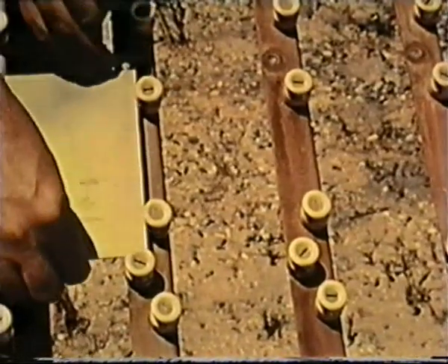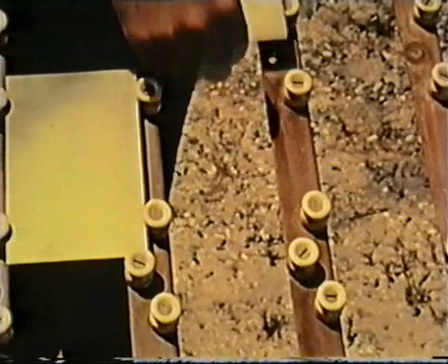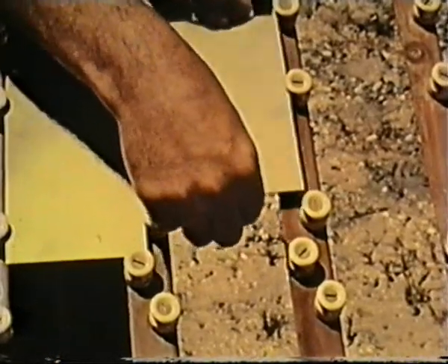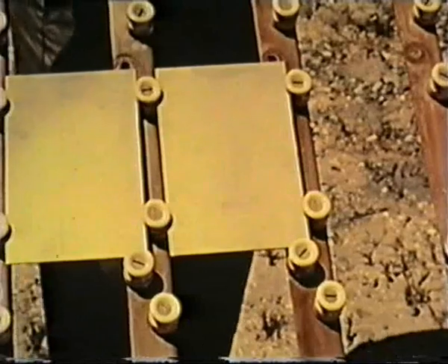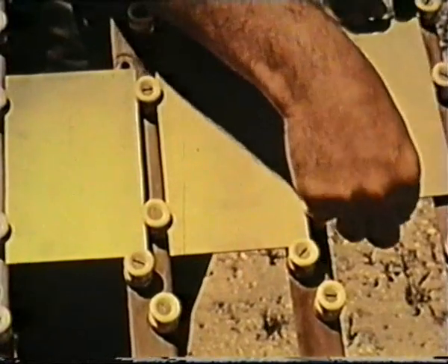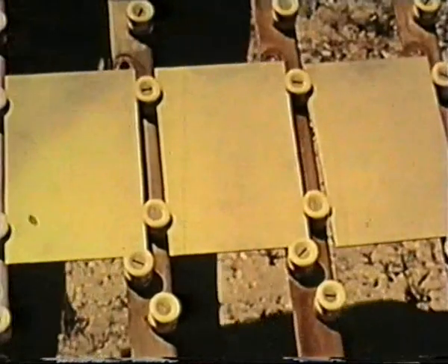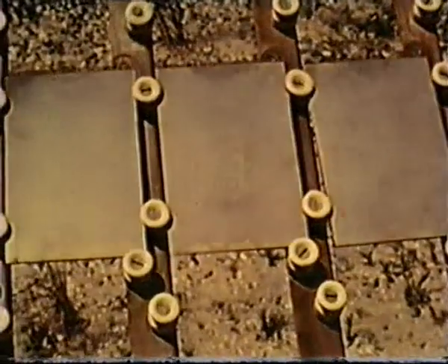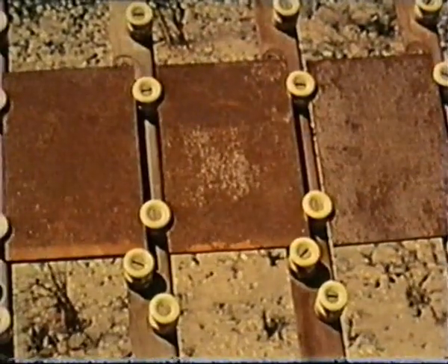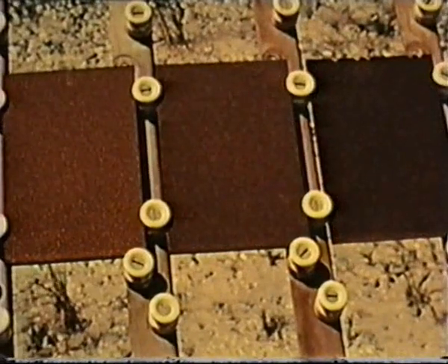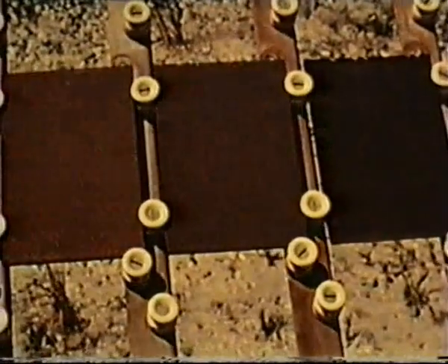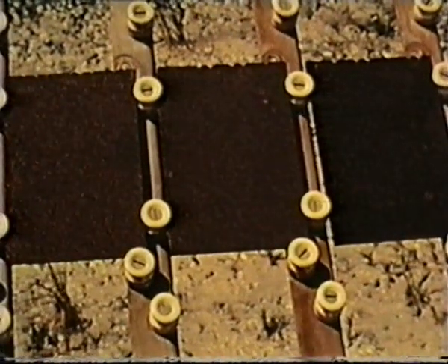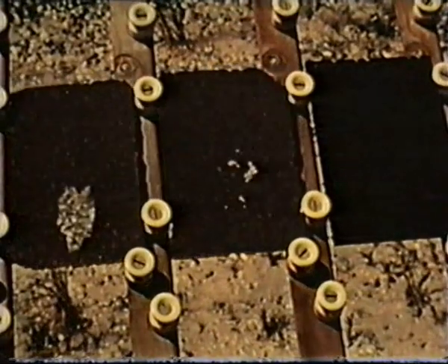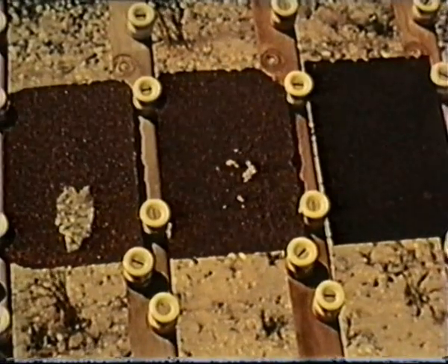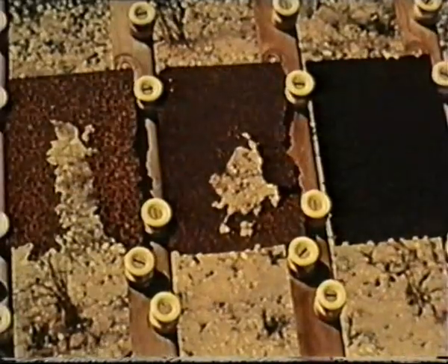The one at the left is a steel of exceptionally low copper content. The one in the middle is an ordinary steel. And the one at the right is a nickel copper chromium steel. Notice the progress of rusting of these 3 steels during their exposure at Kure Beach for 3 years. The differences are due primarily to differences in the protective qualities of their rusts as a result of the addition of alloying elements.